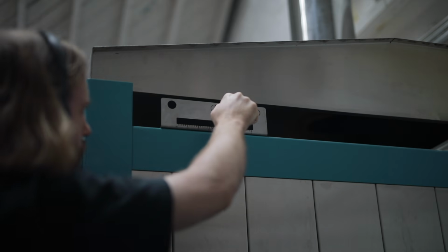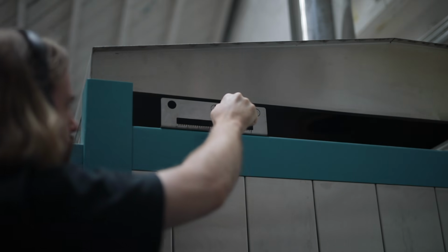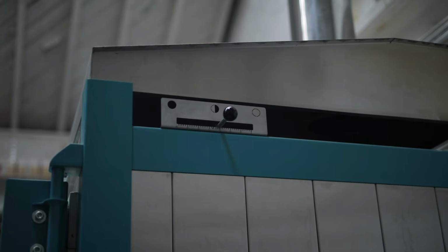Nothing too notable happens during the firing until I hit 860 degrees Celsius. At that point, I initiate reduction by greatly increasing the gas pressure, air pressure, and sliding the dampers that cover the back of the kiln's flues to half closed. This causes the atmosphere inside to change drastically. The burning fuel inside the kiln no longer has enough oxygen to burn efficiently with.